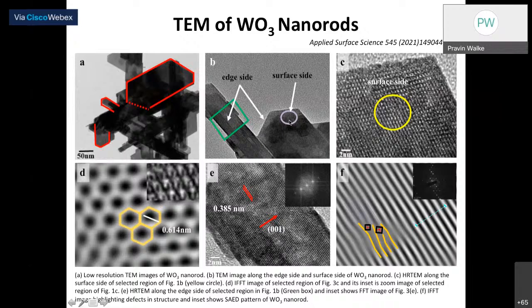If you improve the magnification a little bit, you can clearly see there is a porous network on the surface, right? So this kind of TEM imaging can be taken for simulation, and after the simulation we can extract more information about that particular specimen or sample. Here in case of this WO3 nanorod, what we observed is, let's look at the surface. If you go on the surface and maximize it, you will see there is a little porous network and orderly organized pores, right?